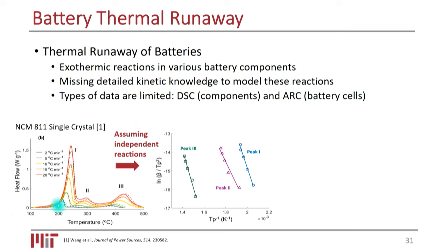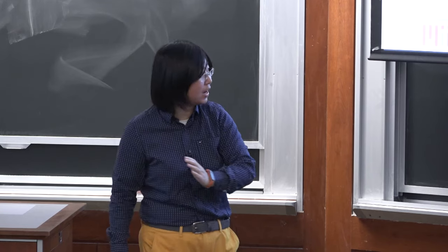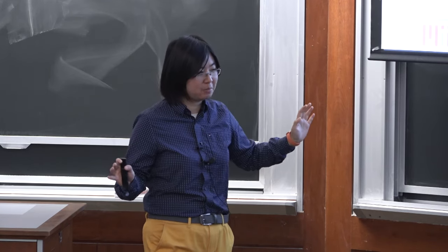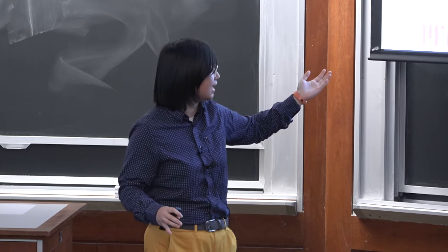But I want to first walk you through this figure, that this is obtained in the DSC experiments I just showed you. The different colors correspond to different heating rates. And the reason why we need to have different heating rates is to perform the Kissinger analysis. So first we need to identify 1, 2, 3. There are three peaks, and we need to assume that each peak would correspond to a single reaction. And they are independent from each other, such that we can use a Kissinger analysis.